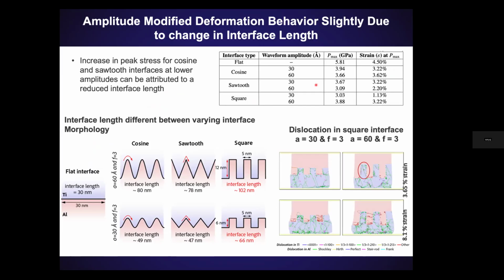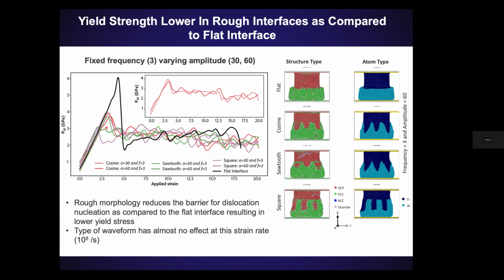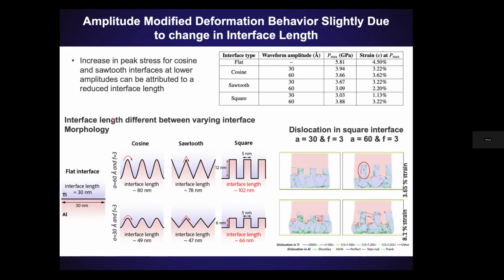Okay, so in the older work, we were trying to figure out whether the shape of the interface matters: cosine versus sawtooth versus square. If I go back and zoom in here, it's within noise, I would say. They look very similar in terms of yield stress. It's not like one is super high versus low. So we were thinking that going from cosine to sawtooth to square maybe doesn't have an effect on the stress-strain response at the strain rates we're at. However, if you change the amplitude within a certain shape, for example in the cosine, a large amplitude versus a smaller amplitude, 60 angstrom to 30 angstrom, my peak stress would change somewhat. It's a pretty small difference, but it was changing, and we wanted to see why amplitude would have an effect at all.